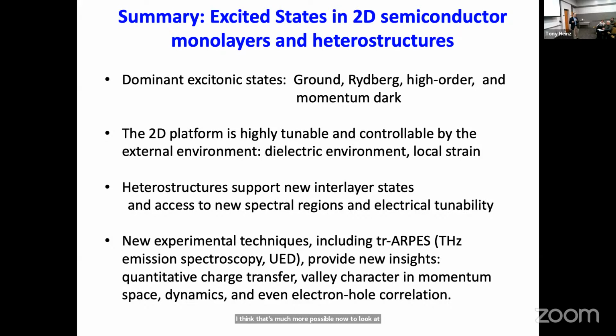And actually, you didn't see so many of the early wide spectra. Of course, our narrow spectra are extremely wide for guys like you by n orders of magnitude. But for solids, they're narrow. But there's been a lot of improvement just by making the external dielectric environment more homogeneous. That was actually the major factor that gave rise to line broadening, because even if the material was perfect, if the external environment was modified, then it would also give you spectral shifts.